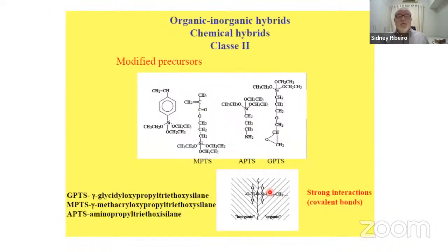And there are the class 2, where we have modified precursors. These are all liquid precursors that we can buy today. They are not expensive. And so what you see here is different functional groups attached to the silicon atom. So you have photopolymerizable precursors. You have here the epoxy group. You have here the vinyl group. You can have amino group. So this is a very rich chemistry that can be done today with no expensive precursors.